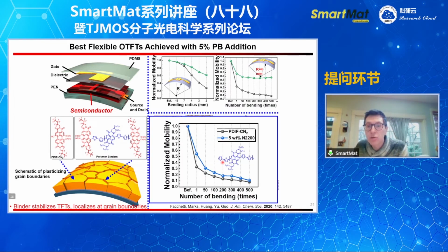And this is a sort of final experiment, right? Because if we add N2200, the mobility continues to decrease. So we don't plasticize the grain boundaries. You really have to have this polymer. This polymer is not good. This is good. Yes. Thank you.